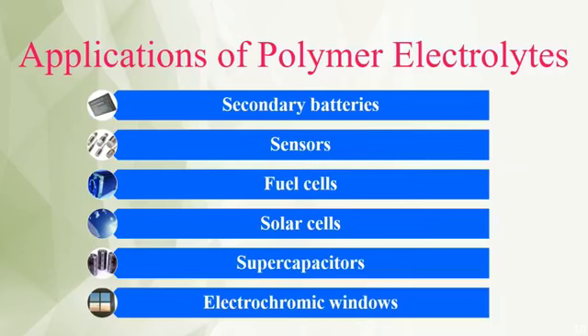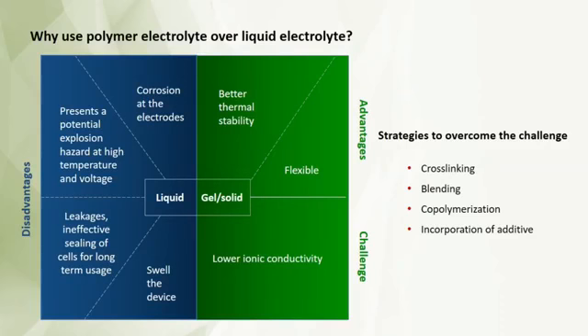Okay, why do we use polymer electrolyte over liquid electrolytes? As I mentioned earlier, liquid electrolytes can cause corrosion at the electrodes, and they also present a potential explosion risk at high temperature and voltage. Because of the liquid electrolyte, leakage is possible, and they can also swell the device. So the option will be polymer electrolytes, which can give us better thermal stability and also high flexibility.